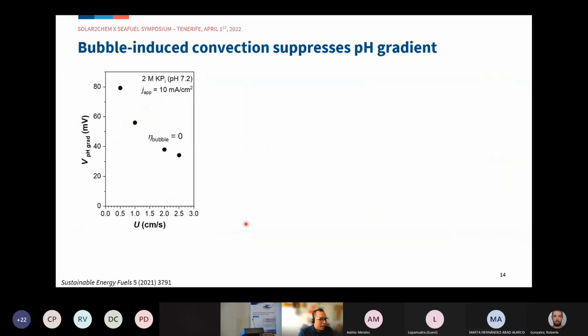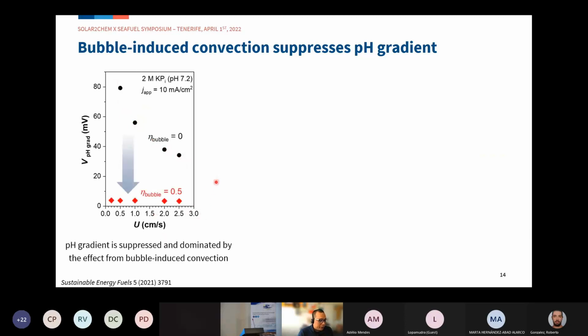We then compare how this bubble-induced convection affects the pH gradient. First, in the case where no bubble formation is considered, we have a certain amount of pH gradient that decreases with increasing inlet velocity or forced convection. But when we introduce bubble formation, we suppress the pH gradient significantly, and we no longer see the effect of inlet velocity—it's dominated by bubble-induced convection.